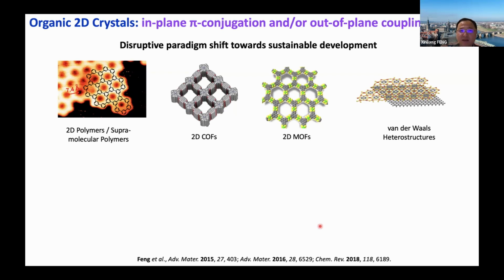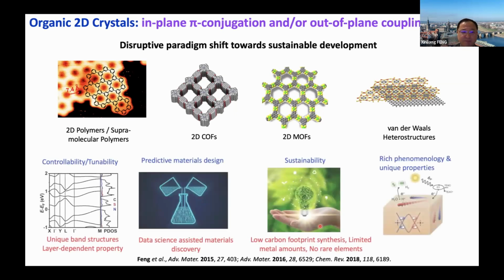So basically, we have been very much focusing on these organic 2D crystals, that is, organic layer material, which have the interesting highly conjugated structures and with the strong interlayer coupling that we are looking for to tune the property of these types of materials. So the advantage of this material is that they can be synthetically controllable and tunable, because you can do the bottom-up synthesis to tune their property, and you can have a unique electronic band structure for this material, and it shows the layer-dependent property, which is pretty unique for organic materials.